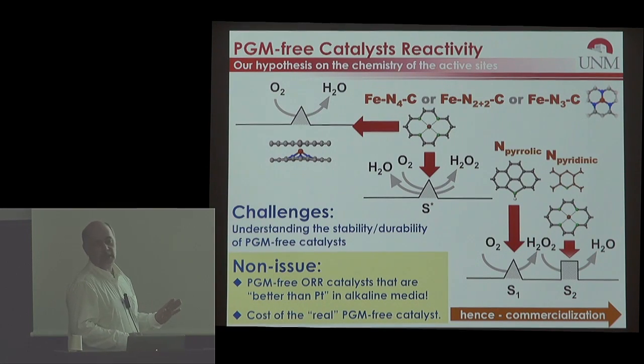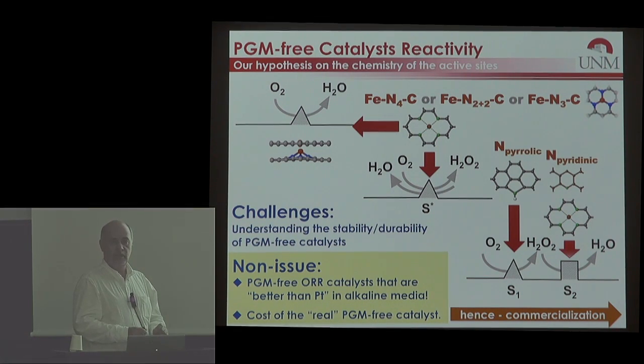What we clearly can say is that there is more than one active site with a comparable activity. We computed them all with DFT, and they have very similar binding energies and very similar activities. And more than one mechanism is usually supported on the catalyst: on unsuccessful catalysts, these two mechanisms, and on successful catalysts, these two mechanisms. So you do not have a material with a single active site, because the active site is actually a defect in that material.